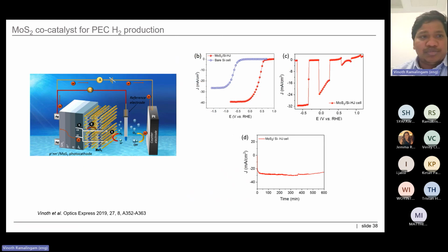This is another project where we used MoS2 as a co-catalyst for photoelectrochemical hydrogen production. This is with the silicon heterojunction. This is the bare cell. See, the performance is really low and the overpotential is really high. But when we couple MoS2 to it, then the overpotential is decreased a lot and the current density increased.